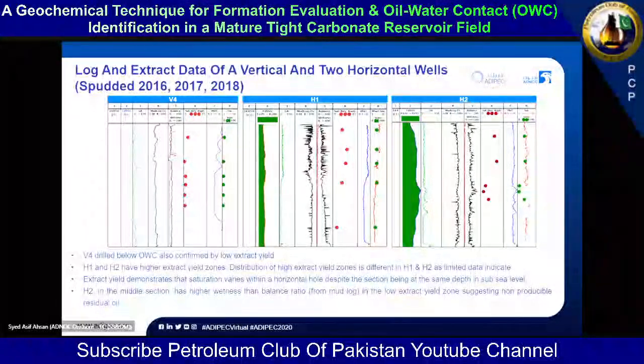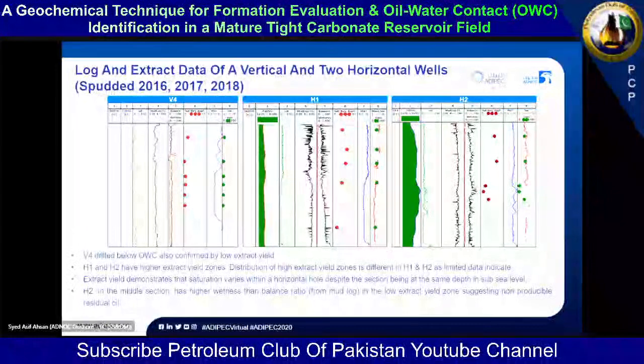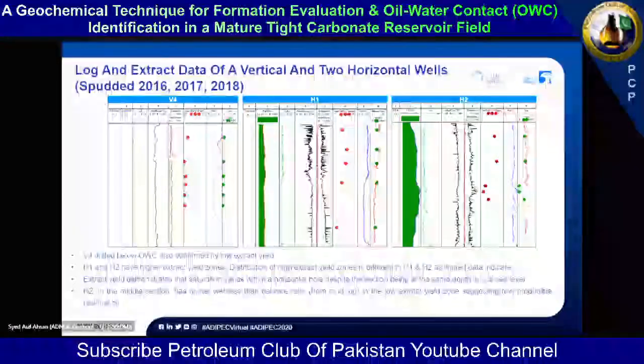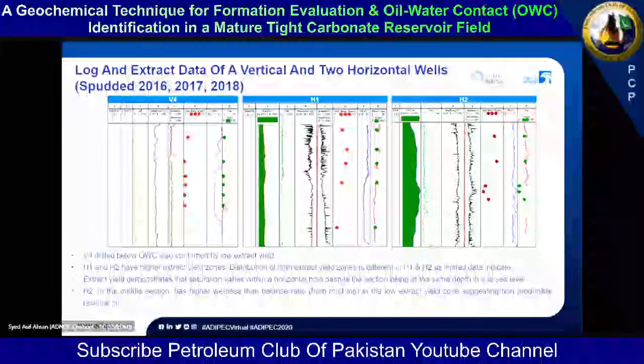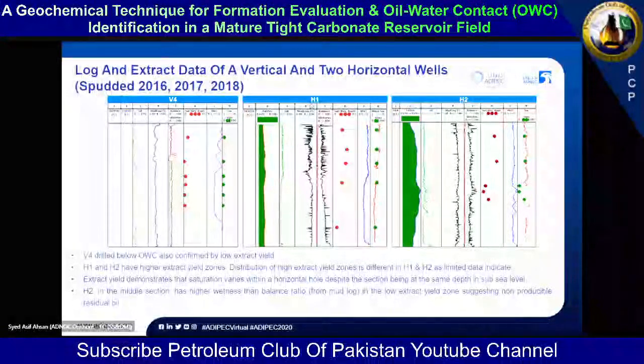Here are three wells again. V4 is a vertical well, and I showed you that well was drilled below the oil water contact, below the base case. So the entire extent of that vertical well was below the oil water contact, and you are seeing that very low extract yield has been observed in these samples, as represented by these green dots.